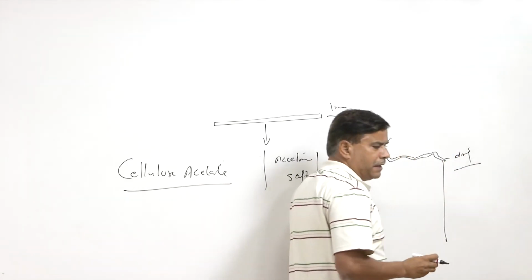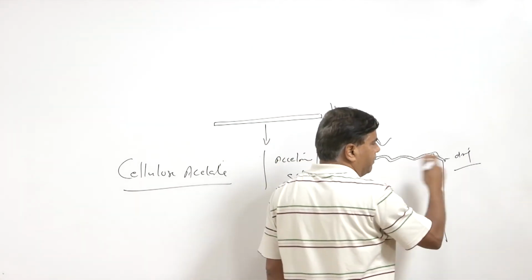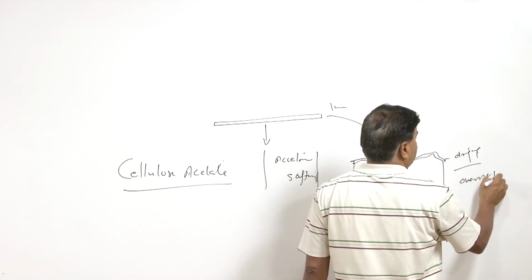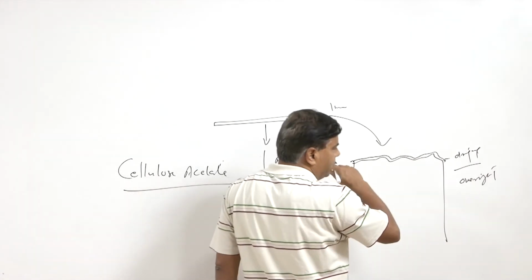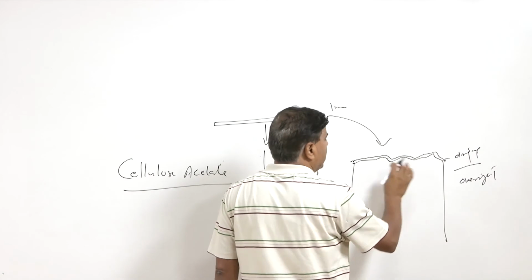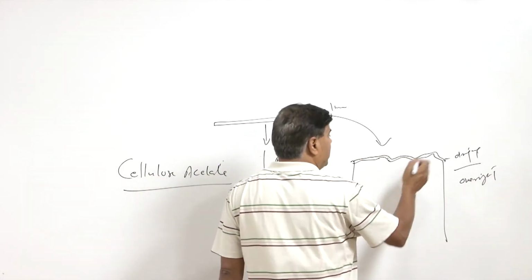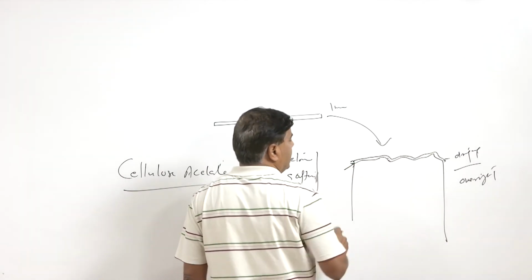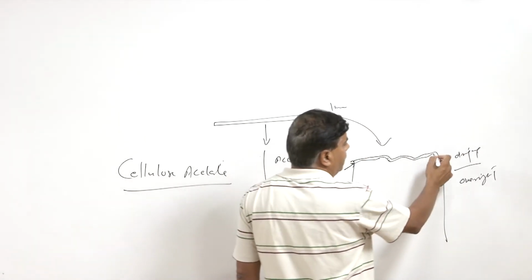Normally, 4 to 10 hours may be given for drying, or just overnight exposure, so that it dries out. When it dries out, all the impurities present on the surface cling and adhere to this sheet, and once they adhere, the sheet is stripped off the sample.